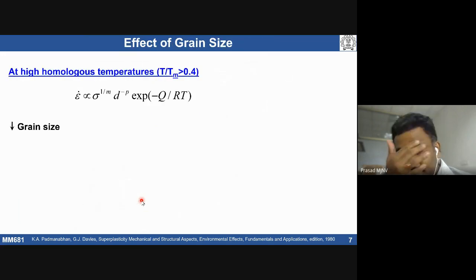See, we talk about high temperature behavior at high homologous temperatures, greater than 0.4 to 0.5 times the melting point. We use a constitutive equation almost similar to what we see in creep deformation, the steady state creep, the Bird-Mukherjee-Dorn equation, which tells us the strain rate depends on stress, grain size, and temperature. These are constitutive parameters.